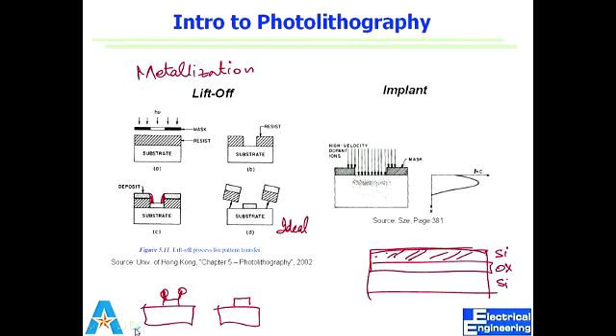This process is called lift-off. So the idea is that we have resist at places where we don't want it. And red is just showing that metal basically makes a film which has this topography to it because there is resist below. Once we expose this to acetone or some chemical which can dissolve resist, we get rid of metal from everywhere where there was resist beneath it. And what we are left with is metal. Right? This is just a two-dimensional figure, but basically what we are getting is a metal line made up from there over the whole substrate. Right?